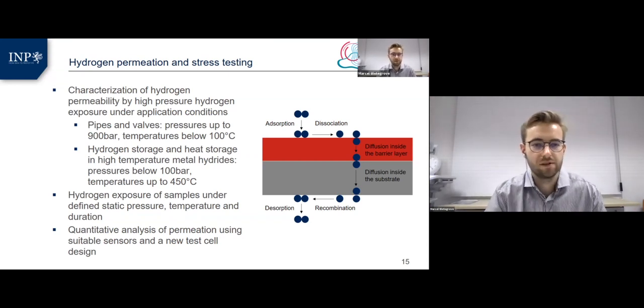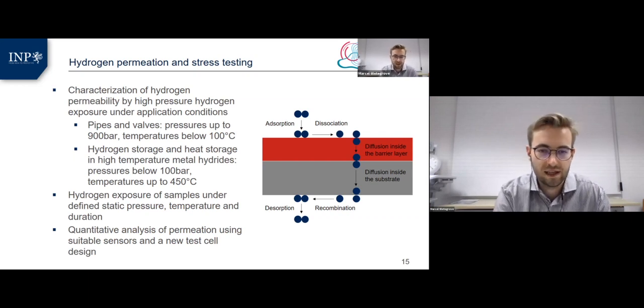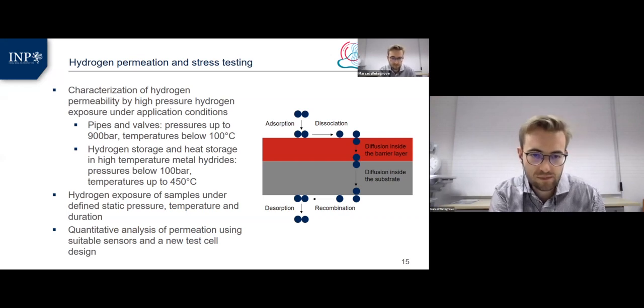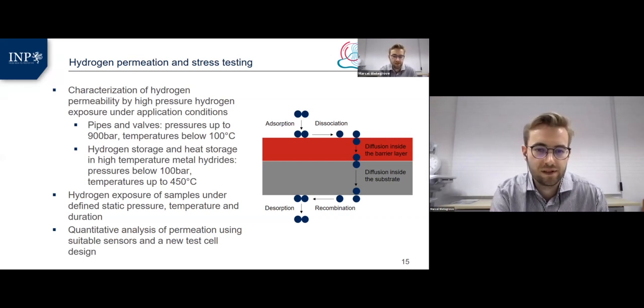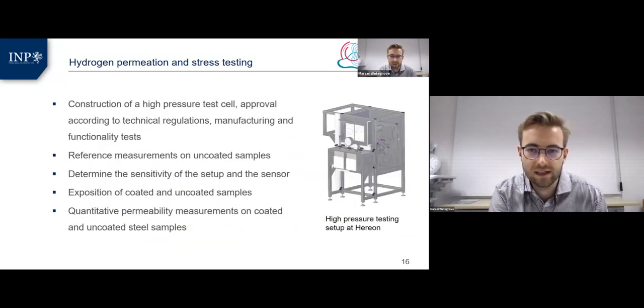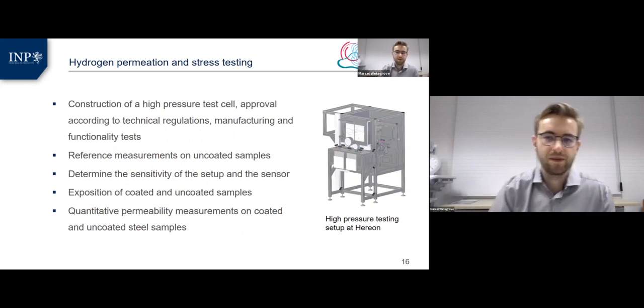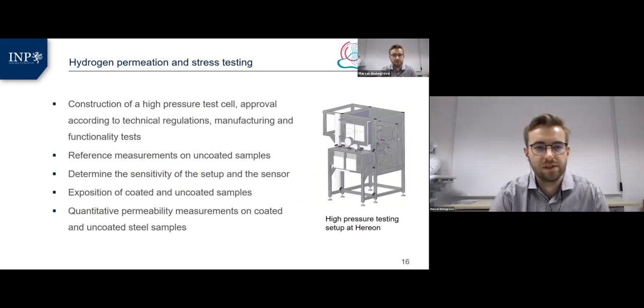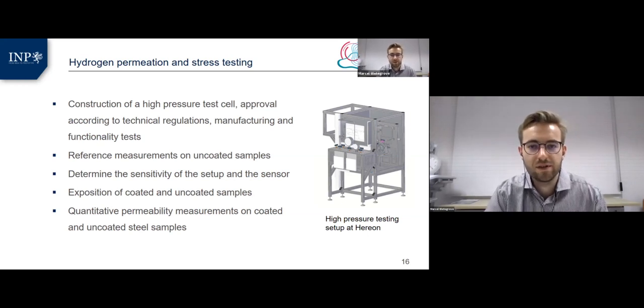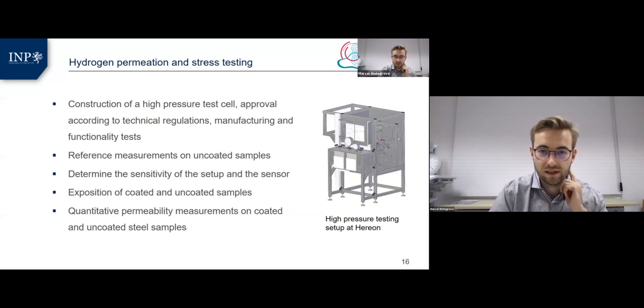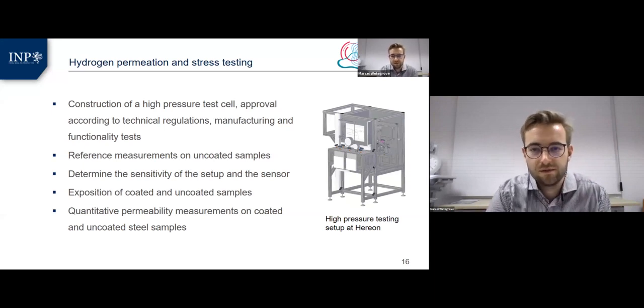Also, Hereon conducts experiments for the exposure of samples under defined static pressure and temperature, and to achieve quantitative analysis of the permeation using a new cell test design and suitable sensors. So this is, I think, a quite sophisticated and large work package to construct a high pressure test cell that is suitable for pressures of up to 900 bars. So this requires approval according to technical regulations and extensive manufacturing and functionality testing efforts.